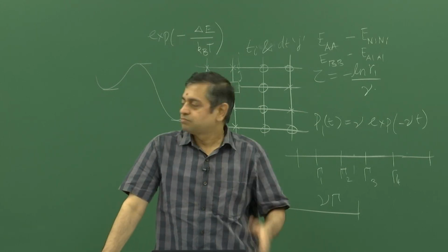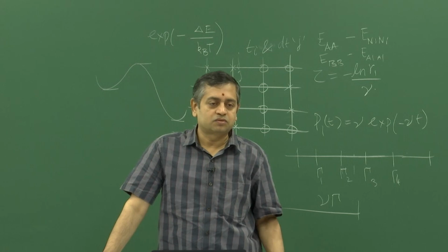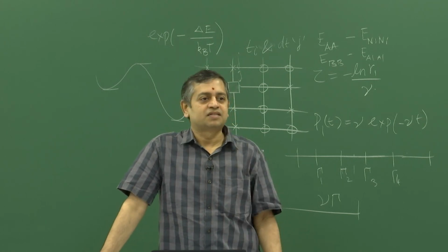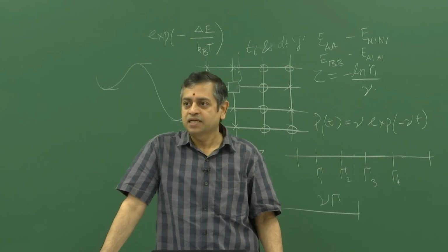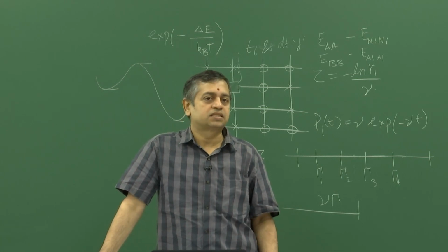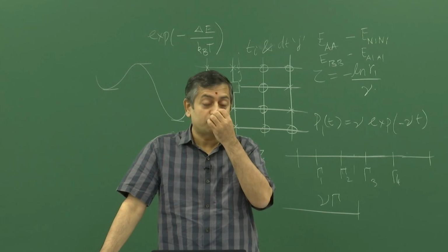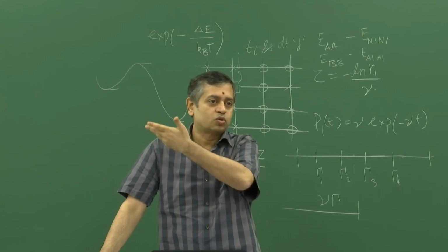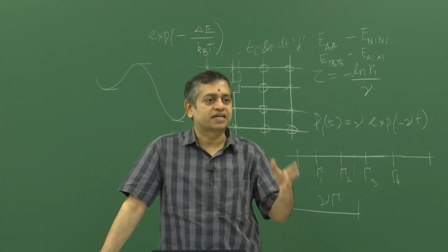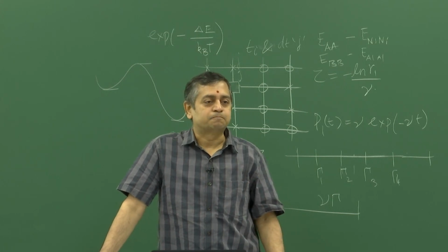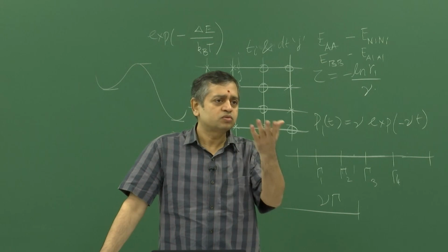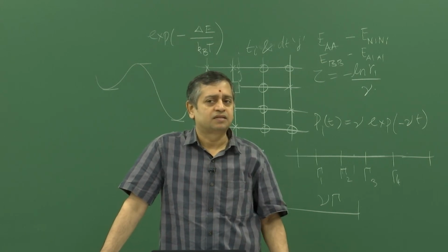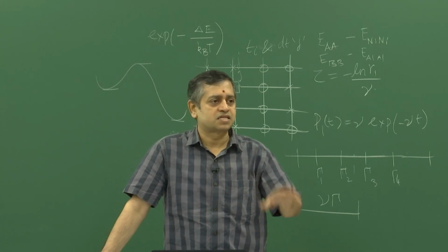But to the extent that these capture many of the physics that you want to model correctly, that is how they are used. So, that is what you should also look up if you want to use a specific system. You look up energies like cohesive energy, vacancy formation energy and so on to calculate these parameters, which you will put into the model, and that will mimic the system that you are looking at.